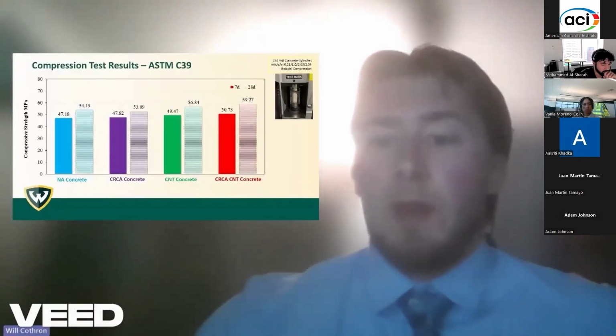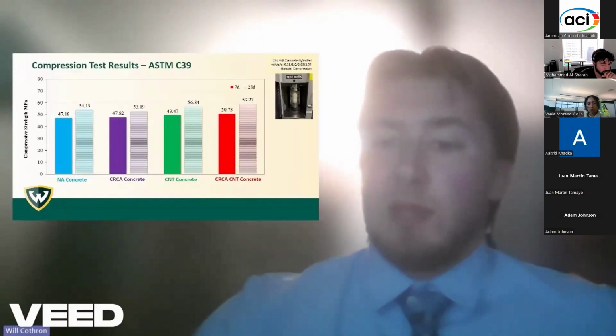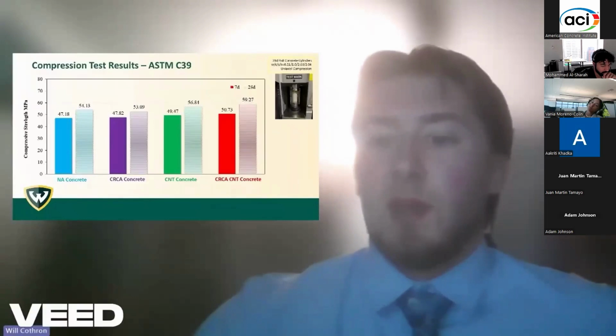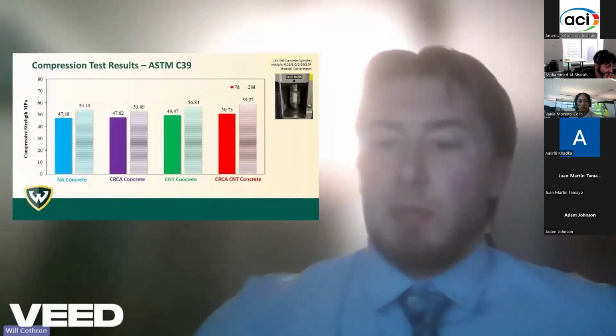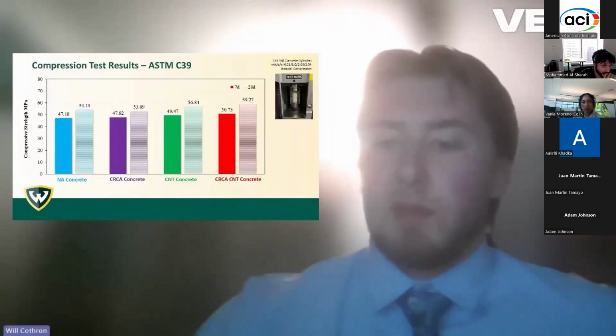in the literature. The combination of CRCA and CNTs exhibits the highest strength of all mixes tested, reaching around 51 MPa at 7 days and exceeding 59 MPa at 28 days. The results indicate that CNT reinforcement effectively compensates for any residual weakness in the recycled aggregates, resulting in a concrete that not only meets structural requirements but also offers enhanced environmental benefits.